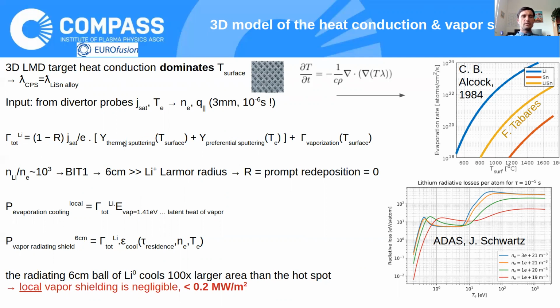And this is what we multiply by the thermal sputtering, which is a function of surface temperature calculated mainly from the heat conduction, plus the preferential sputtering, which is dependent on the temperature of the plasma, plus the vaporization, which is given by the surface temperature again. And this is in fact shown here, the evaporation rate, which rises very strongly, exponentially, with the surface temperature in degrees, calculated either for lithium or lithium-tin alloy or tin itself.